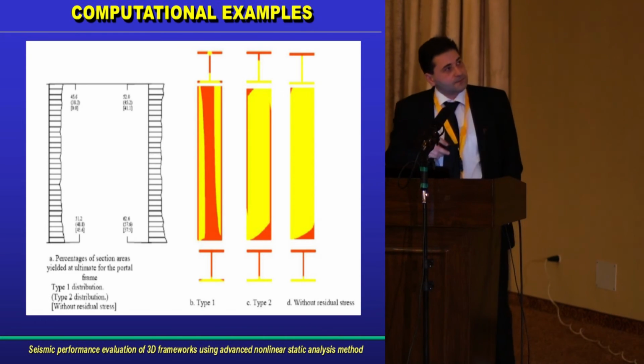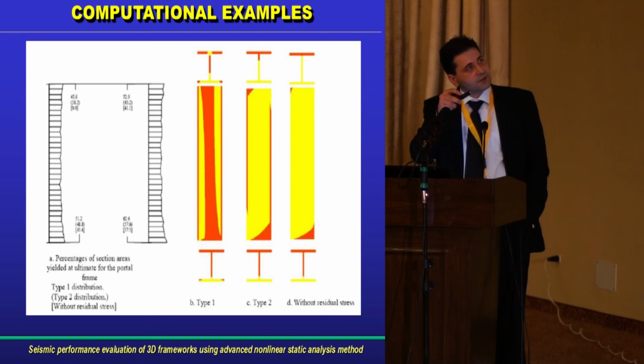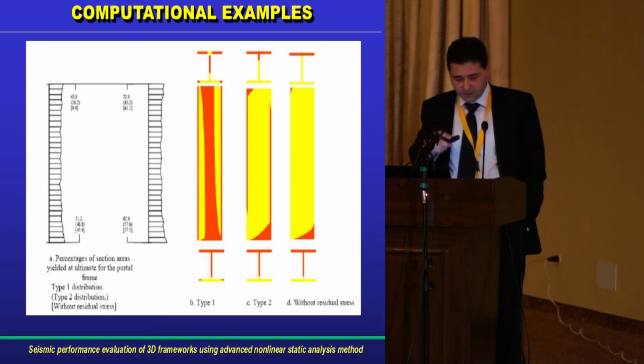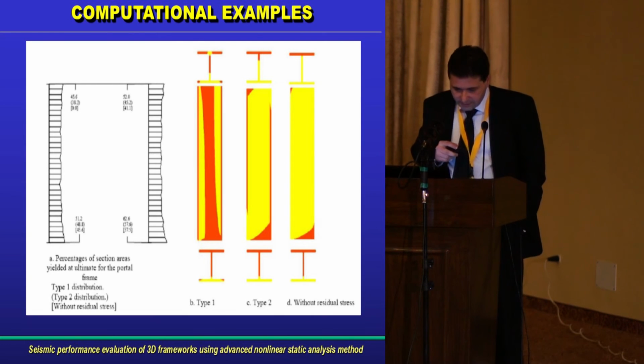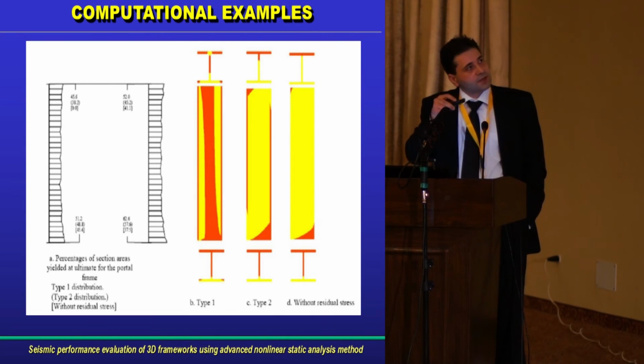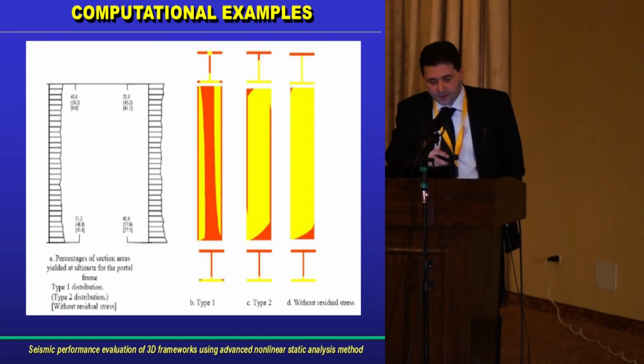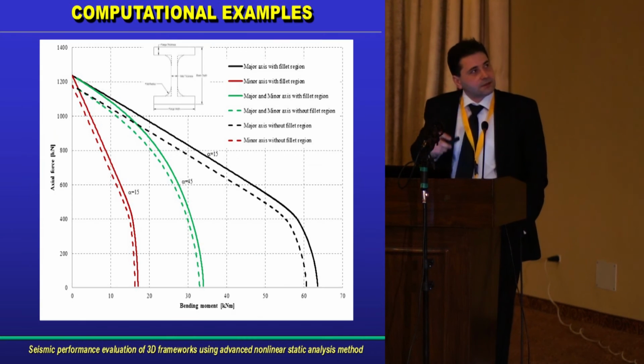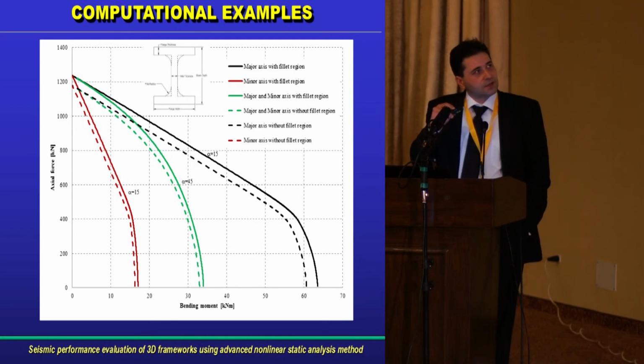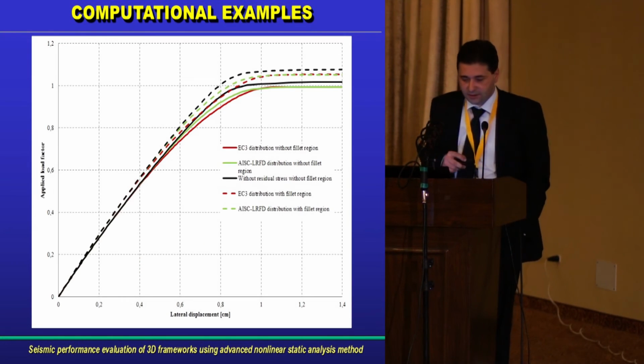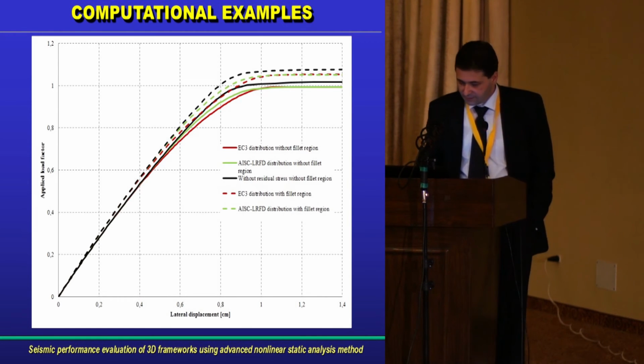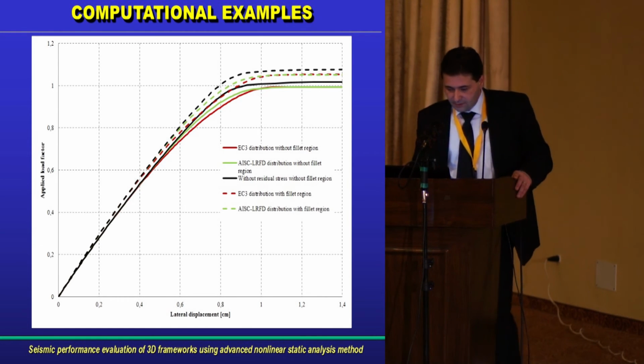For instance, this frame has been analyzed considering three distributions of the residual stresses. This is European distribution, American distribution, and this without considering any residual stresses over the cross sections. We can see here, it's very clear, that the plastifications develop along the entire element lengths if we consider residual stresses.